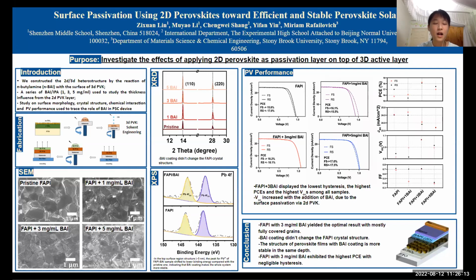Our SEM samples indicated that while pristine samples had defective boundaries, passivated samples had more fully covered grains, with the 3BAI sample yielding the optimal results. Our XRD analysis indicated that BAI coating didn't change the FAPI crystal structure.